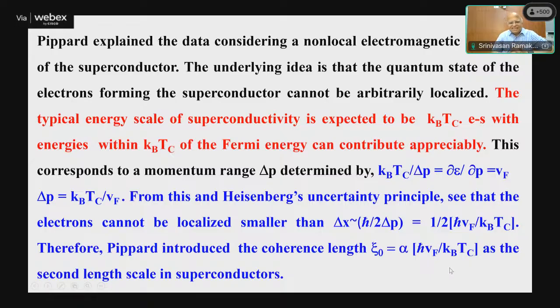The beauty of this is that this is only a thought process. It is completely the intuition of Pippard. The greatest thing is that this matches closely with the BCS theory estimate of the coherence length. So what Pippard did was, from his experimental data, he found that simple one length scale, that is the London penetration depth, is not enough to explain the electromagnetic properties of a superconductor. We need to introduce something known as a coherence length. It is called Pippard's coherence length.